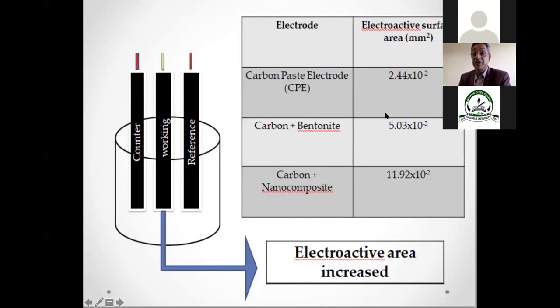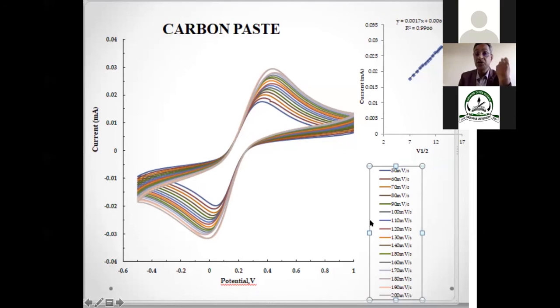So what we will be getting: the carbon paste electrode is 2.44 times 10 to the power minus 2, and carbon plus bentonite is 5.03 times 10 to the power minus 2. When we have taken this nanocomposite, almost 5 times the electroactive surface area has increased. This is our intention, to increase the active surface area. Once it is increased, definitely the LOD we will be getting will be much lower. We'll see how much the LOD will be.